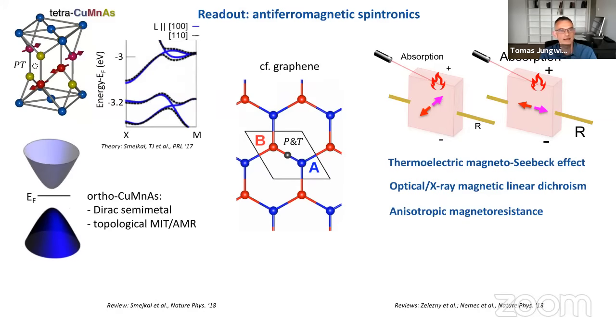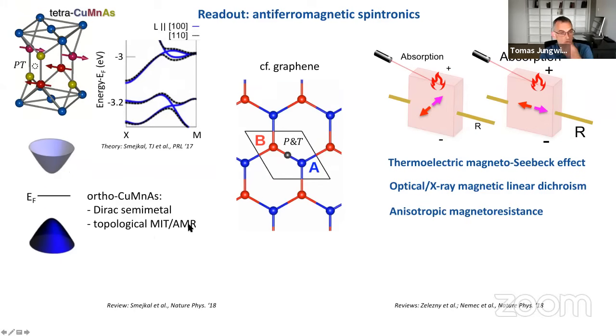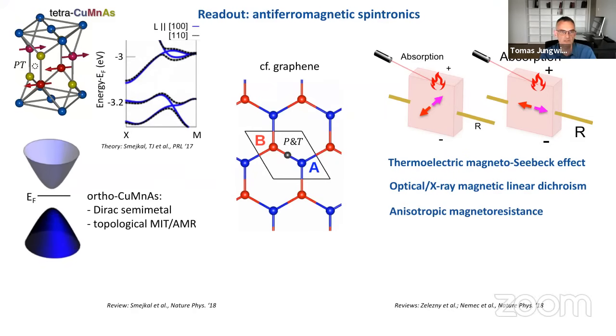So what can happen is that this Dirac point is protected, so there is no hybridization, and we have a true crossing of the two doubly degenerate bands only for the Néel vector orientation or direction along some special high symmetry crystal axes. Once we change the orientation of the Néel vector, this protection of the Dirac crossing is lifted, and we can open a gap. So by just changing the direction of the magnetic moments, we can change the system from a metallic, semi-metallic system into an insulator. And this is due to the reorientation of the magnetic moment. So we have this metal-insulator transition and accompanying, in principle, huge, singular anisotropic magnetoresistance.